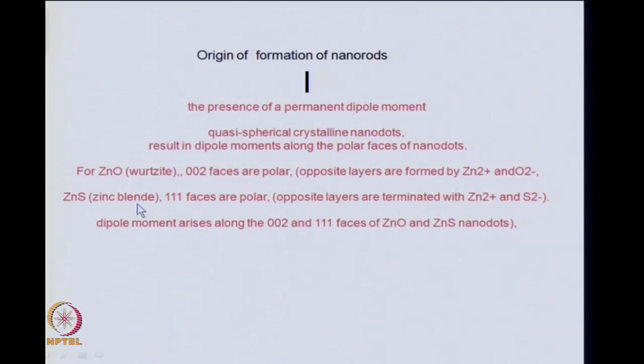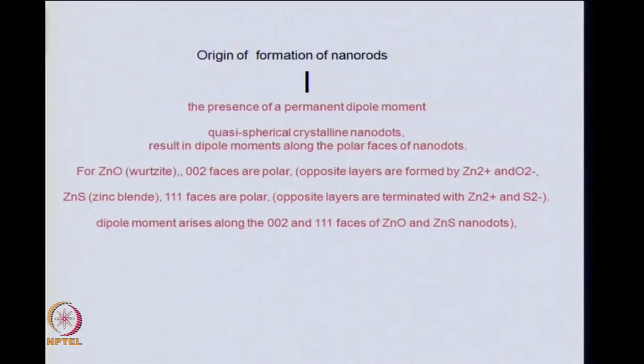In zinc sulfide, which has the zinc blende structure, the 1-1-1 faces are polar. So in this case, opposite 1-1-1 layers will have either positive or negative charges, and accordingly the subsequent ions, say the sulfide ions, will come and attach to the surface which has the positive charge, that means which is terminated by zinc 2 plus ions. And similarly, the zinc 2 plus ions will come and attach to the surface which is terminated by sulfide ions. And this way, the crystal growth will take place in a very oriented manner, and you will have this nanorod formation. So the dipole moment along the 002 face of zinc oxide and the 1-1-1 face of zinc sulfide is important for the growth of nanorods in this system.